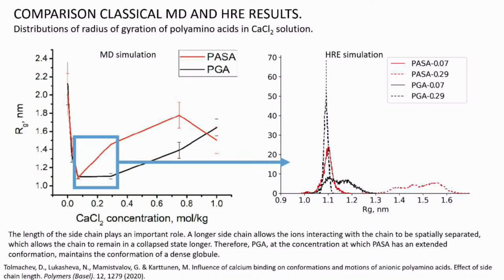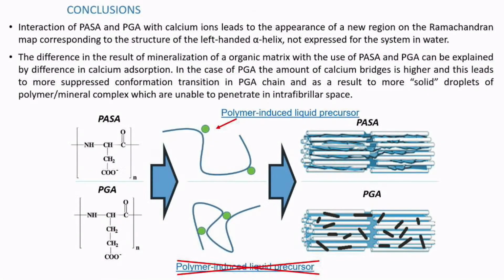But in the case of glutamic acid, the longer side chains allow it to distribute adsorbed calcium ions and to save a collapsed backbone. So this is the reason for such behavior. And we think that these results explain the experimental results that I mentioned at the beginning of my talk.